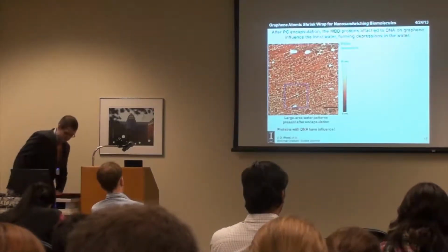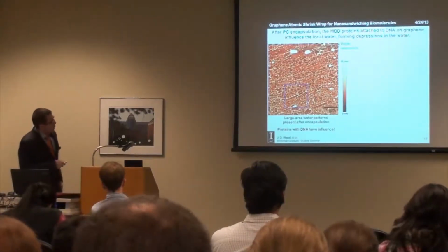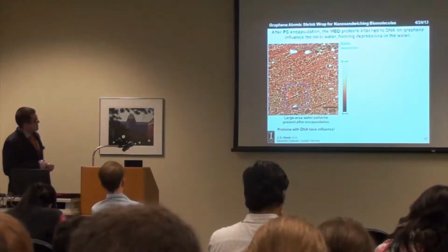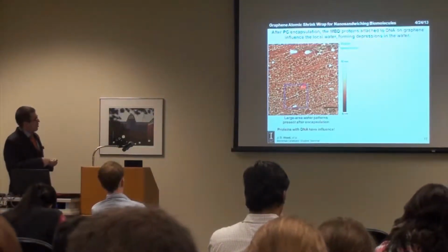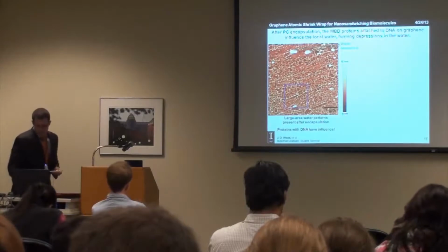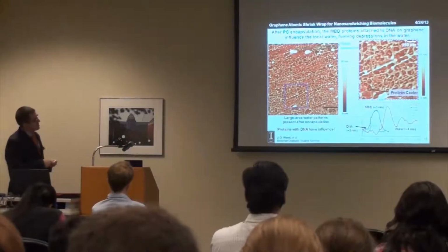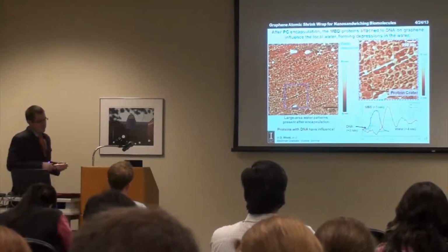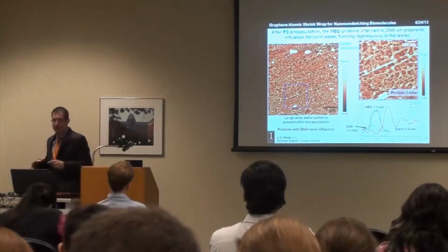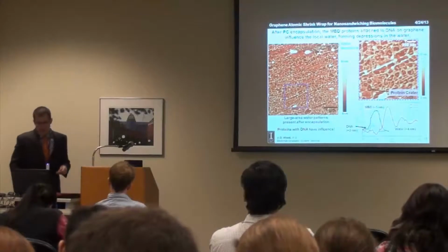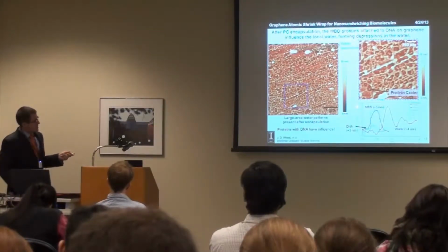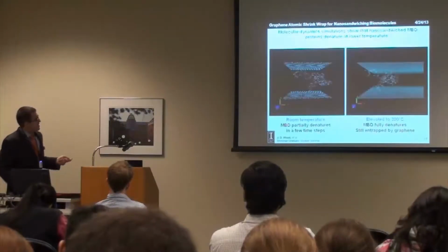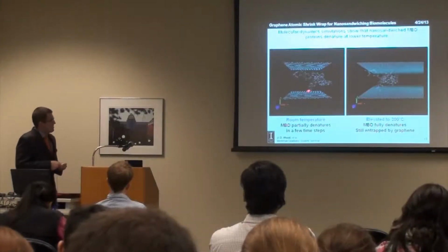And then we put a graphene layer on. Something really bizarre happens. When we put the graphene layer on, we notice that there are these craters, these depressions, all over in the image. And what are these? Well, there's a protein for essentially every single one of these depressions. That is due to the fact that the protein is having a long-range influence on the local water structure around it. Exactly why it's having that is the subject of our future simulations,